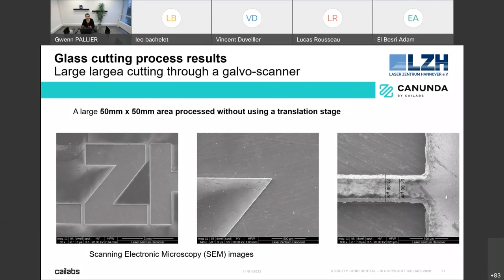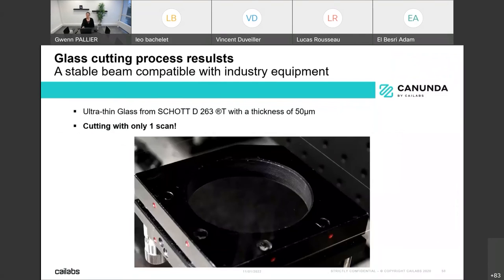What is extremely important to remember from this part of the presentation is that we were processing without a translation stage over 50 by 50 millimeters, which is actually huge. It means that our Bessel beam was getting through a scanner. And this is very difficult because most of the time when you are using a transmissive axicon, it is difficult to have a stable enough beam to get through a scanner. In our case, it was possible, and we managed for one of the first times all over the world to process with a Bessel beam through a scanner.